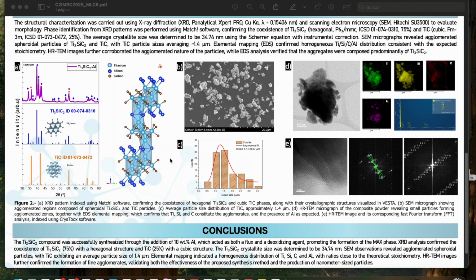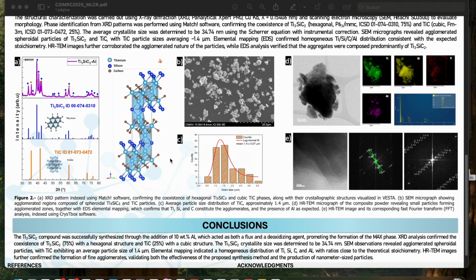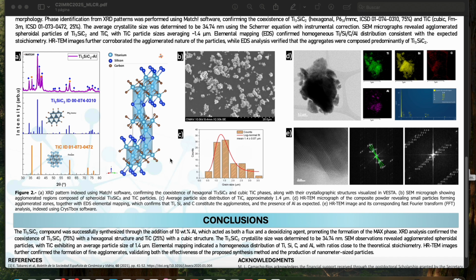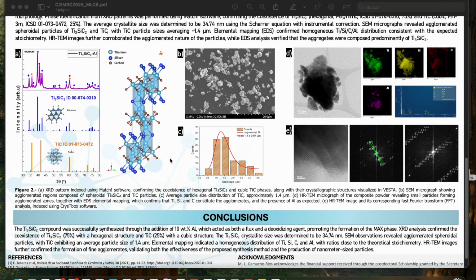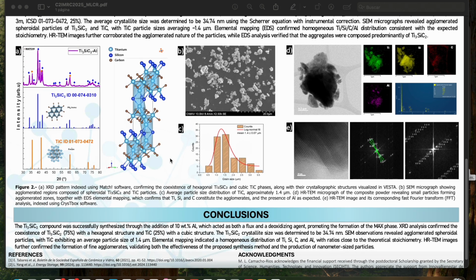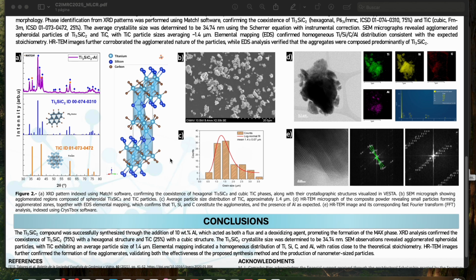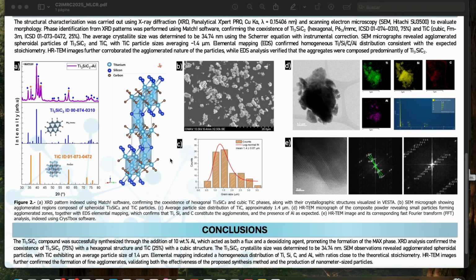The limitations are clear and define the next optimization loop. To further depress TiC, we will tune Al content, wafer thickness, pellet green density, and ignition energy, and we will add simple hold time control. We also plan Rietveld refinement with an internal standard for formal phase quantification, and we will explore pre-alloyed TiSi powders to bias the path toward Ti3SiC2.